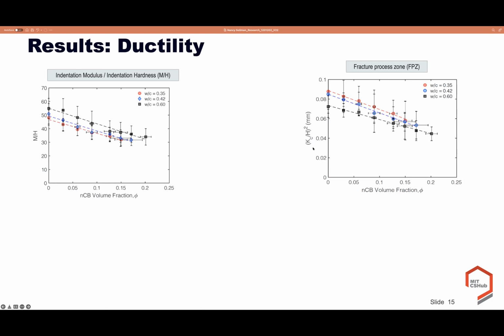The fracture processing zone represents the ductility: if the fracture processing zone is large, the material is ductile, while if the fracture processing zone is small, it means the material is brittle. What we observed here is that the addition of nanocarbon black reduces the ductility of the material, in terms of the indentation modulus over indentation hardness or the fracture processing zone.